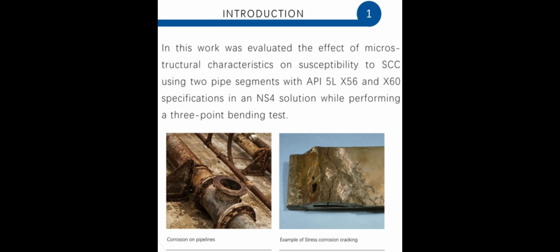This type of stress corrosion cracking is known as non-classical stress corrosion cracking and has been studied to a lesser extent, which is why this work addresses the occurrence of this phenomenon in a near-neutral pH environment. Since stress corrosion cracking is a combination of material, environment, and load, this work evaluates the effect of microstructural characteristics on susceptibility to stress corrosion cracking using two pipe segments with API 5L X56 and X60 specifications in an NS4 near neutral pH solution while performing a 3-point bending test.